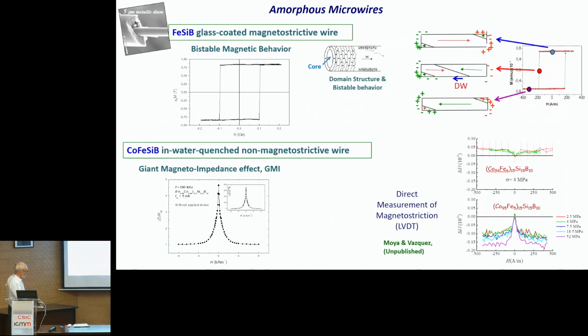Just very roughly, what is the interpretation of this bistable magnetic behavior? We have this square loop. It is practically impossible to obtain an experimental point in this giant Barkhausen jump. The interpretation is that we have a core with axial magnetization, as I mentioned before, and a nearly single domain, but at the very ends of the microwire in the remanence. When we apply that particular value of applied field, we obtain this giant Barkhausen jump: a domain wall moves very fast from one end to the other to get the opposite situation concerning the magnetic domain.